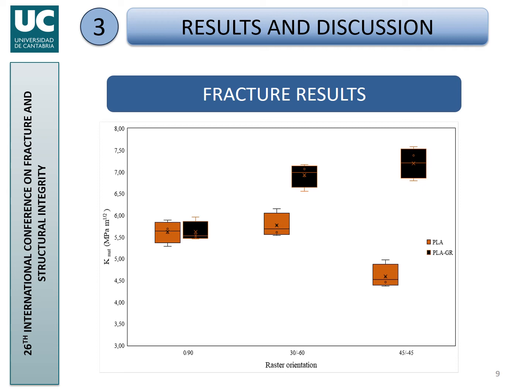However, as long as we change the raster orientations, for the other extreme condition, 45/-45, the addition of graphene provides a high enhancement of the fracture properties, with the 30/-60 raster orientation having also an increase in the fracture properties, but this increase being much more moderate.